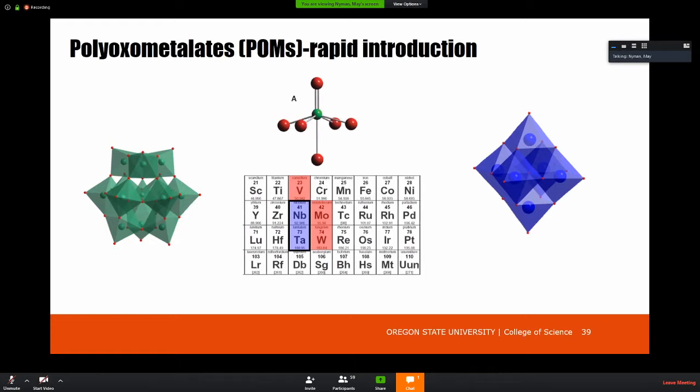Okay, so we could not crystallize these out, and that's why I'm going into this extensive solution characterization. Because, again, we wanted to publish it in JACS, so we needed to understand what's going on. So we turned to the literature, and we had a hypothesis: when you throw the alkalis into solution with the decaniobate, it's shearing off 3 of those octahedra, so we get this Nb7 intermediate with 3 terminal oxos that are very reactive, so it links together in this Nb24 ring. This was crystallized in 2006 with copper amine counterions.